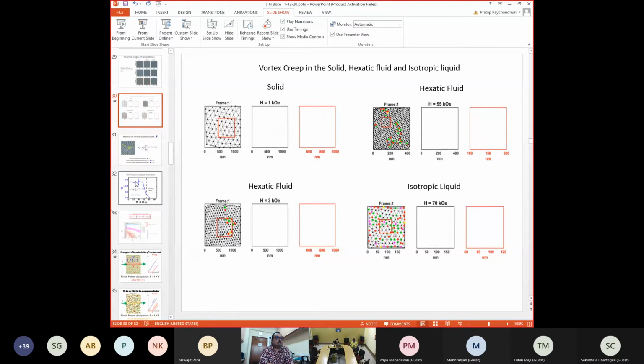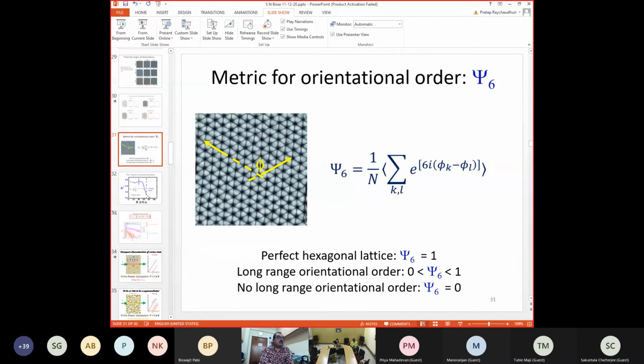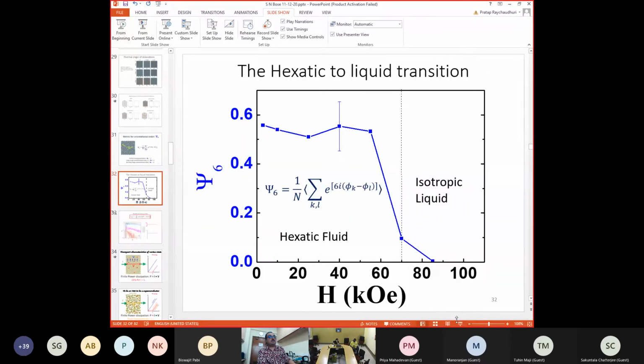We can also calculate the metric of orientational order, which is the Psi6. And then what we observe is that if at 2 Kelvin I increase the magnetic field, this Psi6 is finite up to, let's say, 55 kilo Ørsted. At 70 kilo Ørsted, it rapidly crashes close to 0. Okay, so from our dynamics, we have found the hexatic fluid and the isotropic liquid.